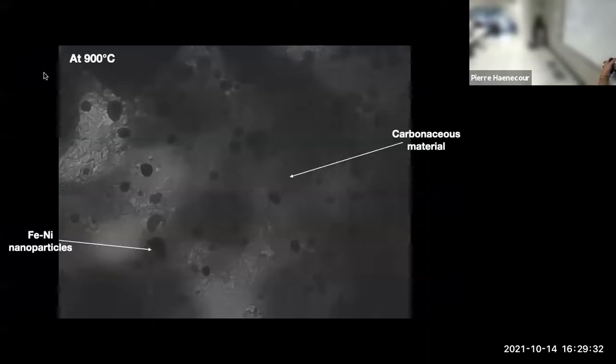I'm going to show you a short movie. The movie was acquired live at 900 degrees. We are stable at 900 degrees, showing you what's happening to those iron nickel particles. The matrix around here is the carbonaceous matter, and this material is iron nickel nanoparticles. I'm particularly showing you that one that you are going to see swim around. It's accelerated, so it was run over several minutes, and I'm going to show you in just a few seconds what's actually happening.